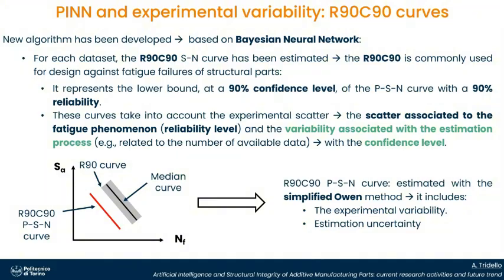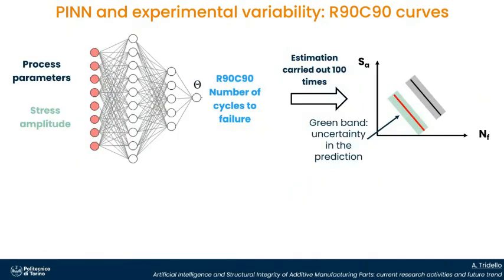Okay, these curves take into account two types of scatter: the scatter associated with the fatigue phenomenon, with the reliability level, and the variability associated with the estimation process, with the confidence level. We estimate this one by shifting this curve, the median curve, by a factor according to the simplified Owen method, which is widely known in the literature, and we can take this very conservative curve used for the design. It is important to remark that this curve takes into account experimental variability and estimation uncertainty. We add another type of variability.